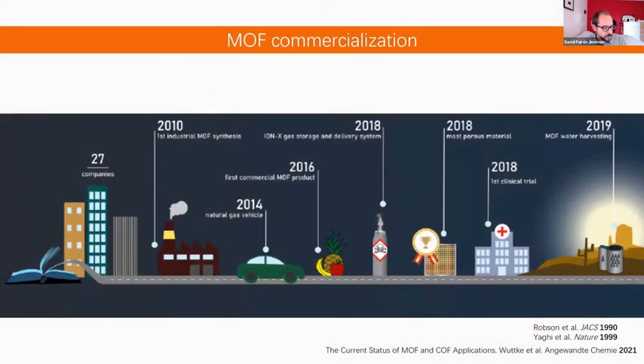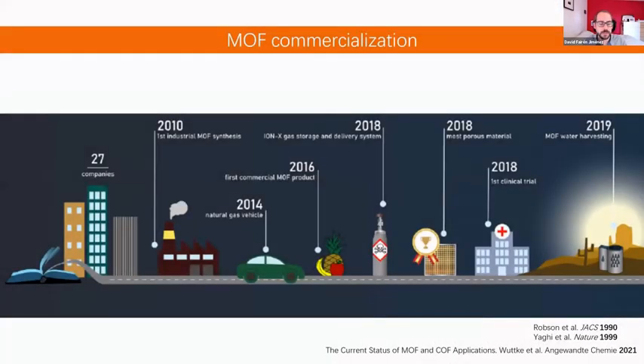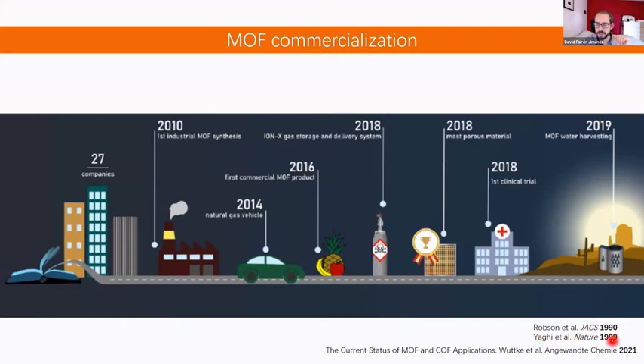So now, just looking a little bit at the literature, okay? And I'm referring to this paper that Professor Wuttke from the Basque Country was publishing this summer. You can really see an evolution of the MOF commercialization in the last years, okay? MOFs were reported, I mean, the name was coined by Professor Yaghi in 1999, okay? Although people were talking about these materials at least 10 years before him, okay? He was creating MOF5 in 1999. There was another paper in Science for HKUST-1 that was also basically the first metal organic framework with porosity measured. So few people created this material, let's say about 20 years ago, okay? Or 10, 20, 25 or 30 years ago.